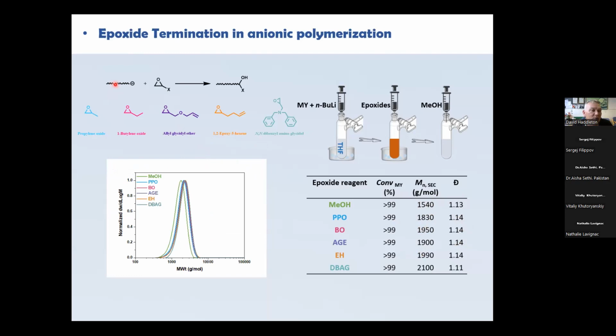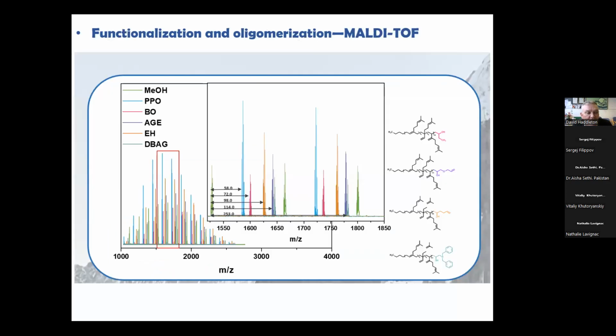And then you can terminate that just by a ring opening with propylene oxide, butylene oxide, any epoxide, and you change the molecular weight a little bit, but you get very good dispersant. And this is myrcene with a variety of different end groups, and you see by the MALDI that as we terminate with different things, we just add that molecular weight, and it's perfect, 100%, especially at this molecular weight, which is quite low. We can even get primary amines. This will then give you a primary amine after a deprotection, and so this allows us to control the end group much better than living radical, to be honest.